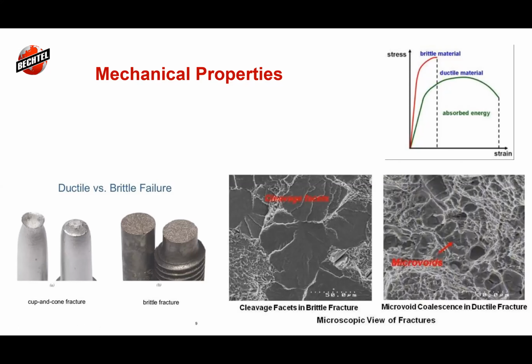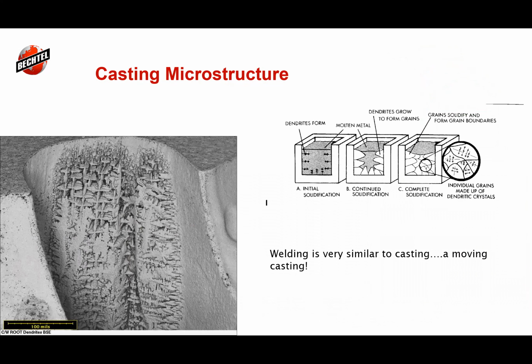Okay, and this is where we get into the heat affected zone regions. When I talk about welding, I have some really nice pictures here, and I talk about it as a casting microstructure, because when we weld, it's sort of like we're putting metal into the mold. I had the pleasure of going to see Atlas Foundry up in Tacoma with Les, and they do some really impressive castings, and they're really massive. But everyone on the line, we're doing castings every time we're welding, because we're melting the metal up and pouring it in. And as we pour the metal in, it solidifies.